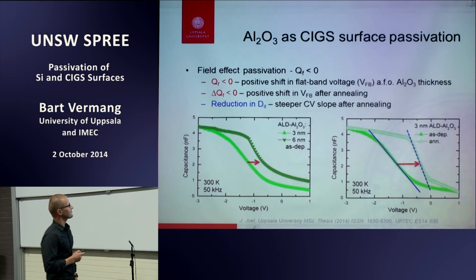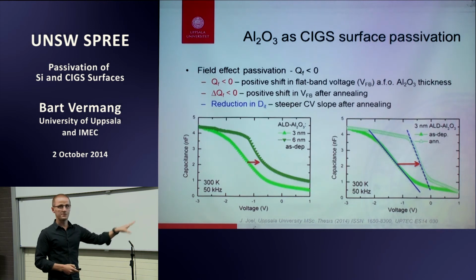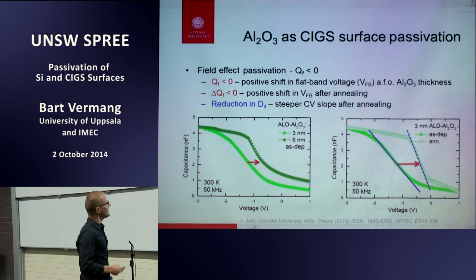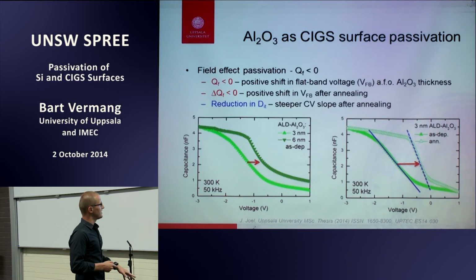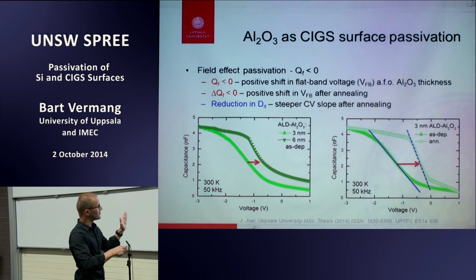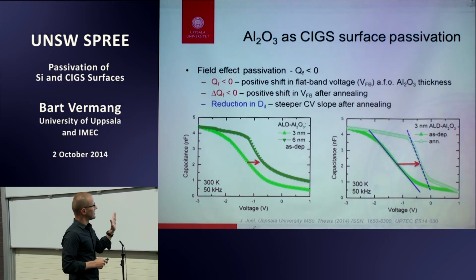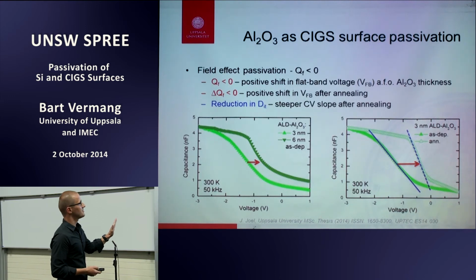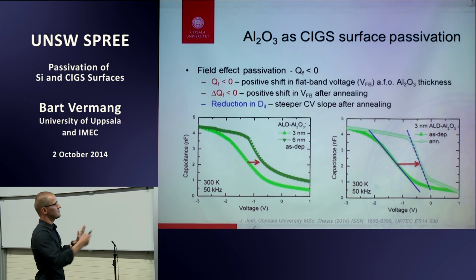As you can see in the next slide, aluminum oxide also gives some negative field effect passivation, it seems, to the CIGS surface. Here you have CV measurements from metal oxide semiconductor devices. The metal is aluminum in this case, the oxide is aluminum oxide, ALD aluminum oxide again, and the semiconductor is CIGS. If you do this on silicon, you get nice CV behavior. These are my best curves. You get worse than this. Anyway, you can see a few indications. In the left picture, we have two different thicknesses, 3 nanometer and 6 nanometer. You can see the flat band voltage, so where you have the inversion or the depletion, shifts to the right as a function of thickness, which is an indication that you have a negative charge within the aluminum oxide. Same thing in the right graph.